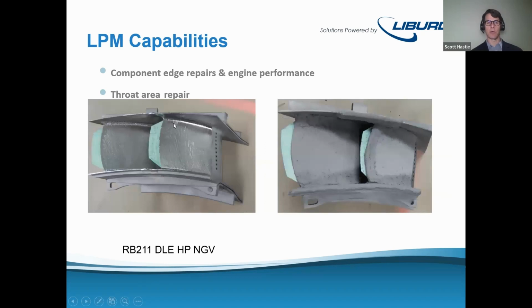We talked a little bit about throat area repair and then repair directly to a trailing edge. And so I wanted to show a couple examples of that where we're using powder metallurgy on this surface. And you can imagine if you were measuring the throat, it would be between this trailing edge and the adjacent airfoil. And so we can adjust that by adding material if it's been worn away through subsequent uses.